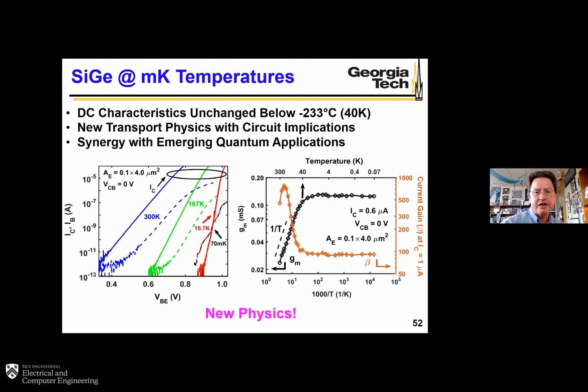This shows us a state-of-the-art silicon-germanium HBT on the left, the IV characteristics, and then the current gain and transconductance on the right. You see that it operates very nicely down to 70 millikelvin, but there is nuanced physics there, which makes it quite interesting. DC characteristics below about 40 Kelvin kind of quench and don't change a whole lot. And what's going on there is new transport physics, which in principle can have implications for circuits. And so this is kind of interesting.